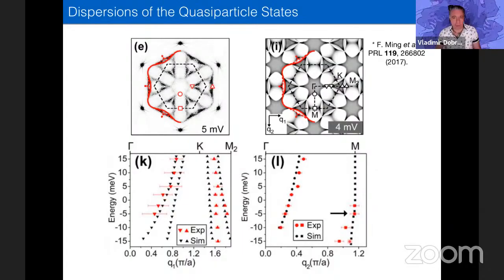But doesn't this correspond formally to having quasi-particles with an effective mass being 1 in the bare mass? That there is no many-body renormalization of the quasi-particle here in this version of the calculation. That's correct. We haven't included any additional effects. So we think that some of that's going to cause some of the flattening of the dispersion, but we don't seem to see anything that looks like a massive band narrowing once the system is about 10% hole doped.